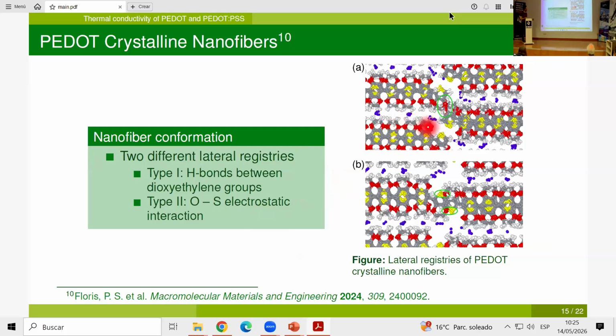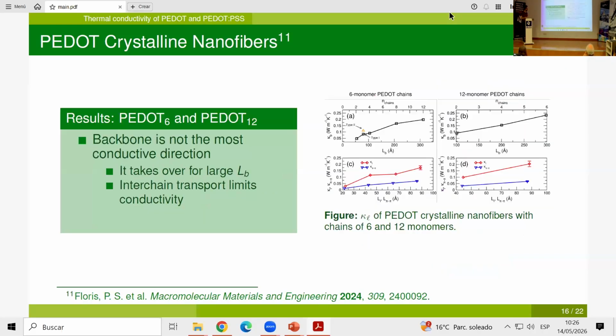During this investigation, first of all, we found that there are two possible lateral registries for PEDOT chains. One is through H bonds between dioxyethylene groups, like you see here, and the other is electrostatic interaction between oxygen and sulfur in this way. Whether the lateral registry is the first or the second also slightly affects thermal conductivity. What we found was a little counterintuitive: the backbone is not the most conductive direction. It only takes over if the nanofiber is long enough. This means that in this kind of system, interchain transport is limiting the thermal conductivity, whereas the pi direction is the least conductive.